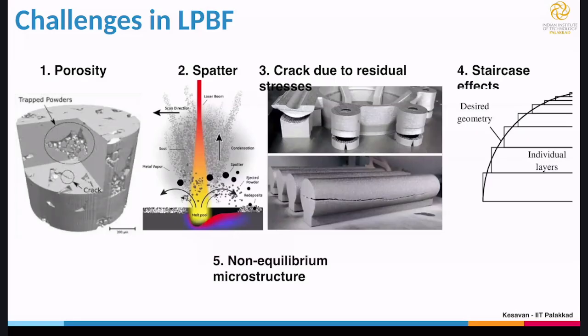Now, of course, spatter is there. Spatter, you can relate to welding. When you perform welding anywhere, you can see there are some spatters. A similar kind of spattering is possible here. And as mentioned, because of layer by layer processing, it leads to a huge amount of stress in the component, and sometimes the stress will reach the critical value that leads to cracking. You can see here that the components are cracked, right? While printing itself, you don't have to pull it. While printing itself, it will be cracking. That's because of the internal stress developed.